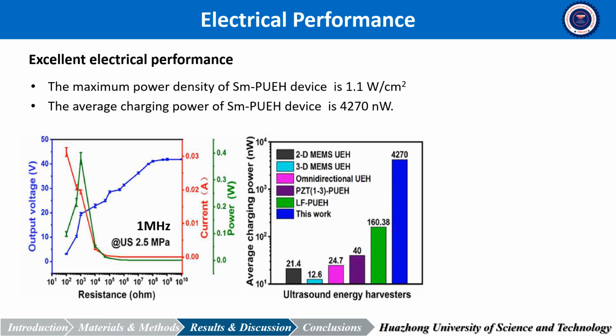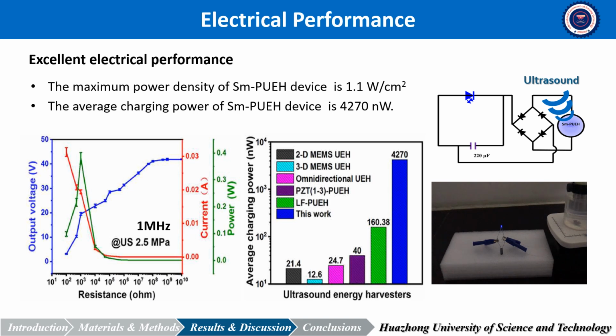The SMPUEH device has excellent electrical performance, driven by 1 MHz ultrasound with the intensity of 2.5 MPa. The maximum power density of our device is 1.1 watt per square centimeter, and its average charging power is 4,270 nanowatt. It's worth noting that both of these values are the highest results reported so far. As you can see, when the ultrasound is applied using our device, one LED can be lit immediately.